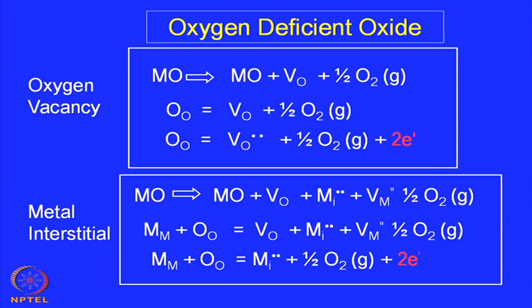Okay. So, all non-stoichiometric oxides are related to the point defect concentration, and depending on the point defect concentration or the nature of the point defect and the kind of non-stoichiometry, you are generating a free electronic charge carrier, which is much more mobile and will give rise to a fairly large conductivity.